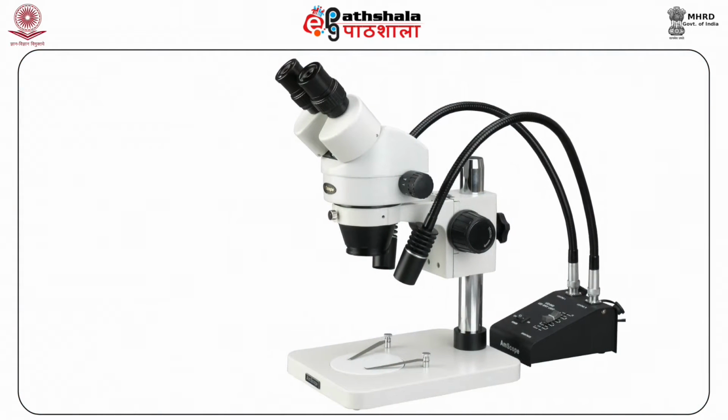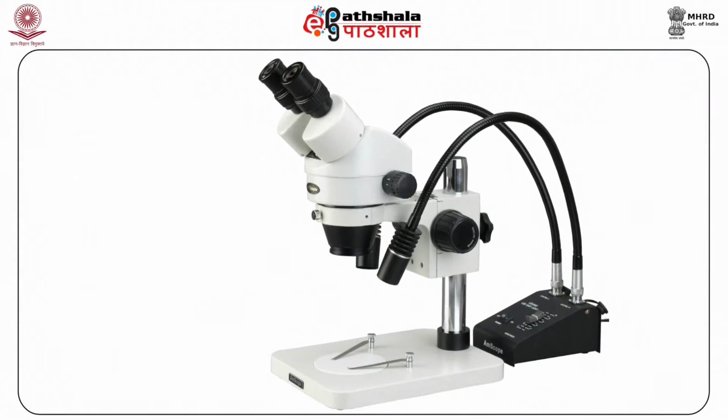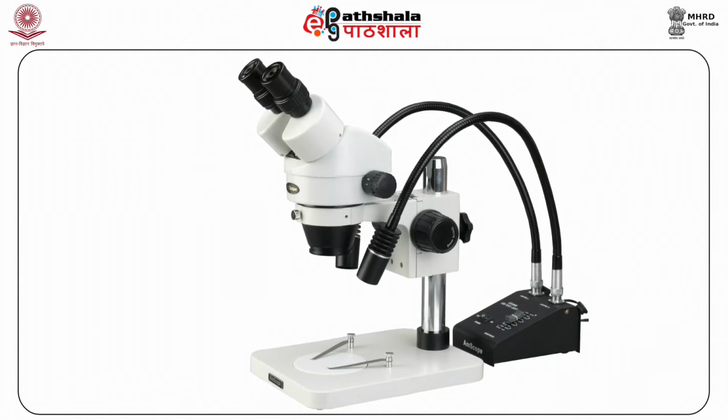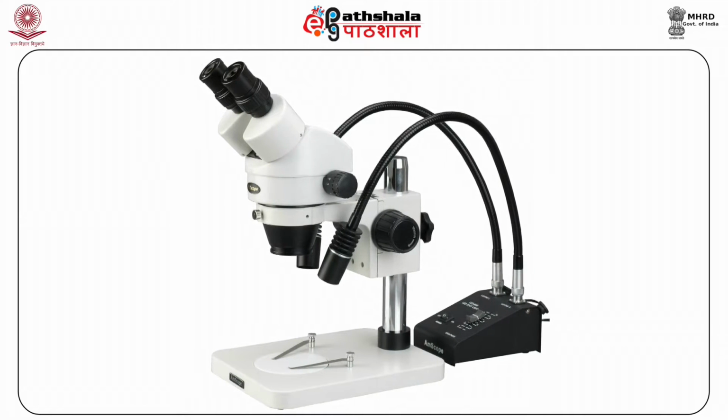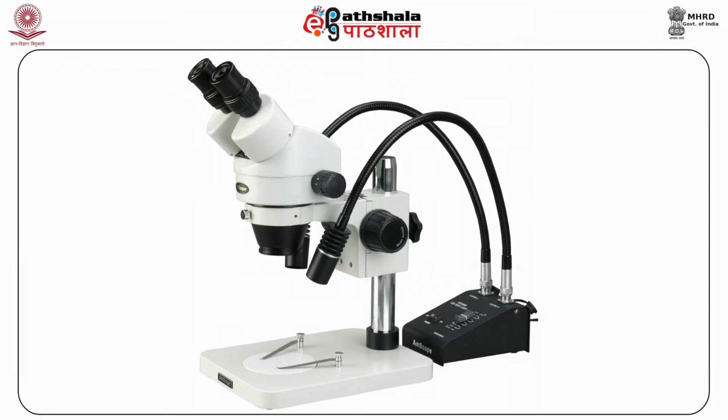Now, a complementary lateral fit along the broken edges over a length of approximately 1/4 of an inch or more will establish whether the two glass fragments were continuous before breakage or not. Now, the match is a three-dimensional match. So, under a stereo microscope, the edges of the samples are carefully and precisely observed, and they will exactly fit into each other.